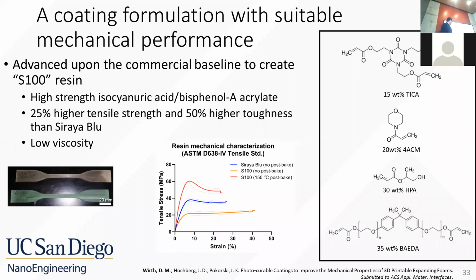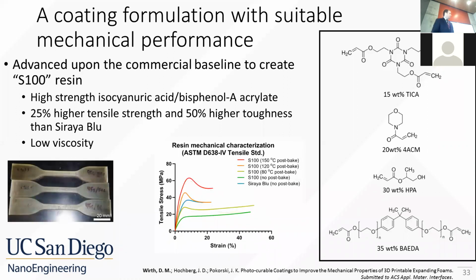If you look here at the mechanical testing results of this resin, as printed tensile testing dog bones, you can see a bit higher toughness than the baseline Siraya Blu. If you post bake it, you can get drastically higher tensile strength. Pulling this thread a little bit and exploring different post bake temperatures, you can actually tune the mechanical properties of this resin by adjusting the post bake temperature.